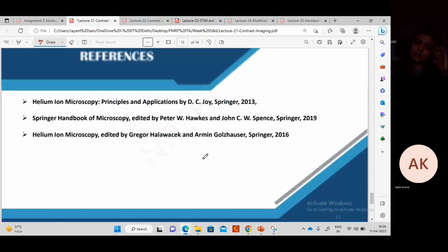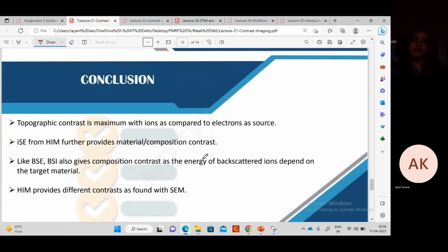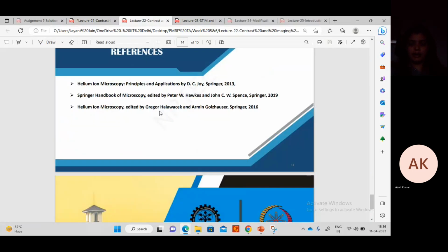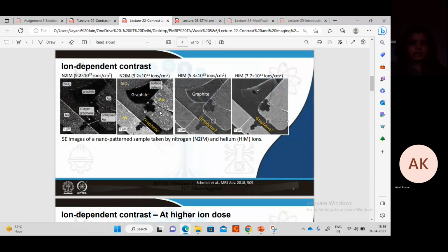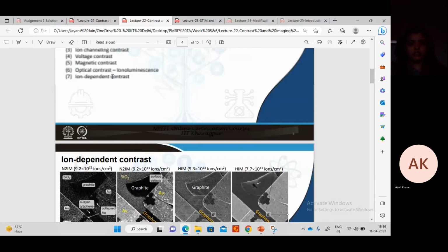Especially if you want to see the BSE image, it's always better to rely on the secondary electron, electron beam, compared to the ion beam, because as you see, not all ions are the same, and not all electrons are the same. As you can see, nitrogen ions will give better contrast in one of the samples that was shown, compared to helium ion. So for getting the BSE image, it is always better to get it in SEM mode, with the electron beam, not the ion beam. That is one point.